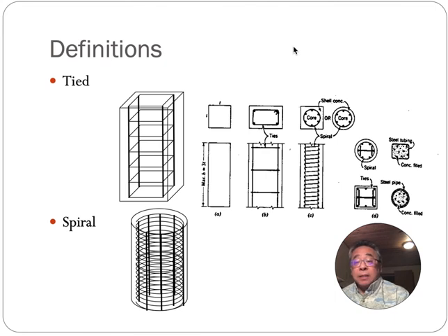Now, it's not a coincidence, because what they did in the Illinois tests was they came up with how far apart you need to put these ties, or how closely you need to space them, to guarantee that you would get an increase in strength that would offset the loss of area. And following those rules was convenient, because then you could just use the gross area.